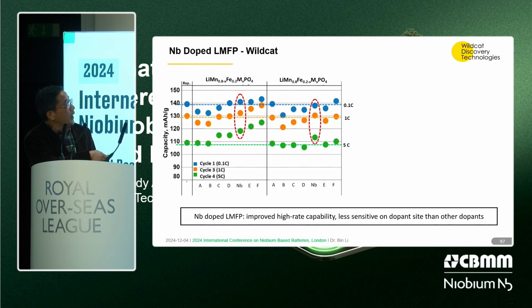We have 7 different kinds of dopings, including niobium. You can see in general, on the manganese side, niobium showed improvement on all of those rates. But for the iron side, niobium is the only element that shows those. Niobium has much more flexibility, or is more robust, in terms of the doping study in these materials.